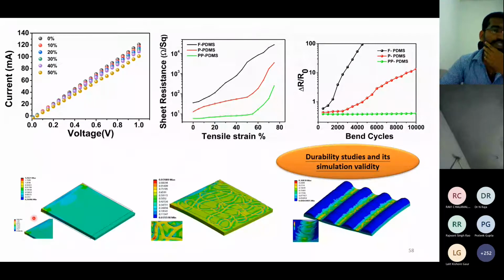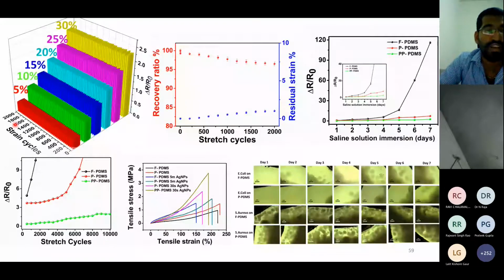And the other one I want to share is the current durability. Here you can see current versus different strain percentages. We do it for 0, 10, 20, like this. We keep straining the device conductive electrodes like this, and then we monitor the IV curve. And then we also check the sheet resistance over different tensile strain and bending cycles. It's quite good. And here we can see the strain studies for 5, 10, 15, 20, what happens up to 2000 cycles we did. And then residual strain and recovery studies.